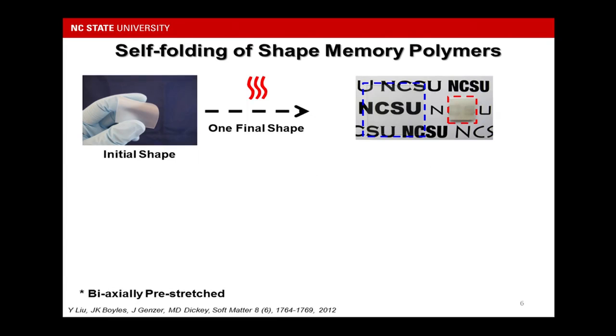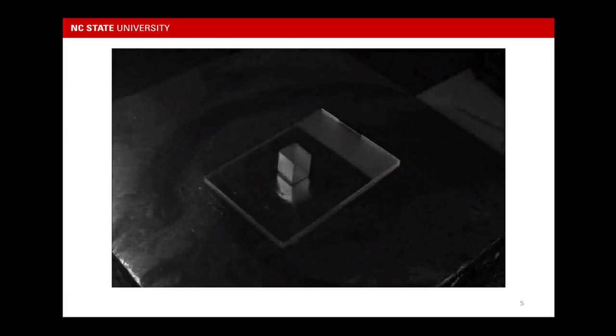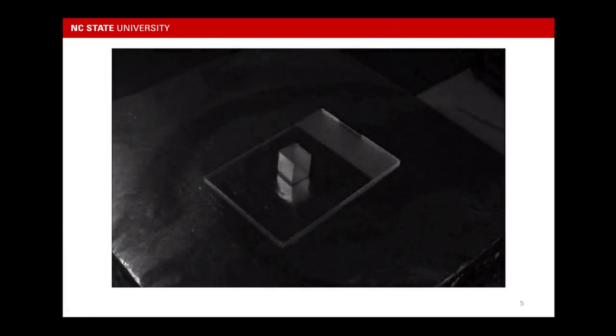So here is an example. I actually brought some samples with me. What we use is this flexible, transparent polymer sheet. We use just a regular printer, with which we can pattern black ink as a template on this polymer sheet. In this video, I will show you quickly. This is a template we cut out from these materials. After exposing it to an IR heat lamp, you can see it will fold directly into 3D structures in seconds without any hands-on facilities. The point is that the printed black ink pattern will selectively absorb the light and convert it into heat to locally heat the polymer and cause shrinkage.